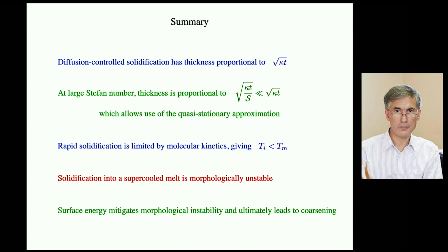So here you either take into account the molecular kinetics or the curvature, you never mix that. Is it possible? Yes, and in fact, if I had done the morphological stability calculation rigorously, really I should have been in the S less than 1 regime, governed by kinetic undercooling, and then included that kinetic undercooling also in my stability analysis.